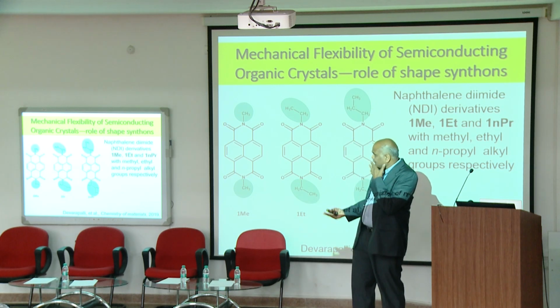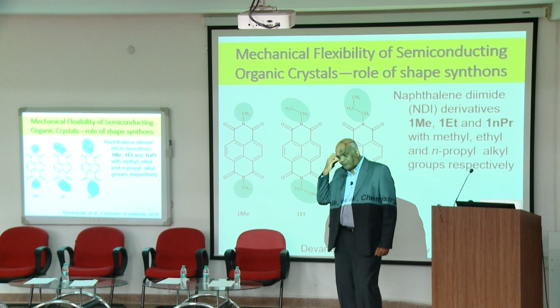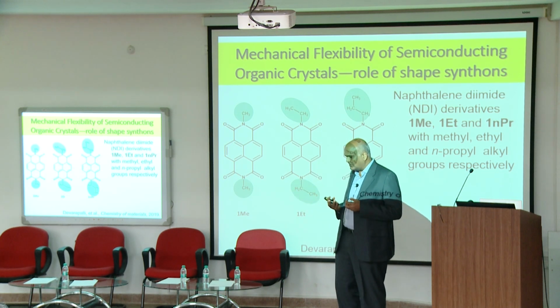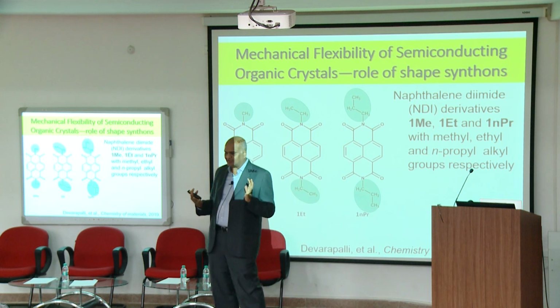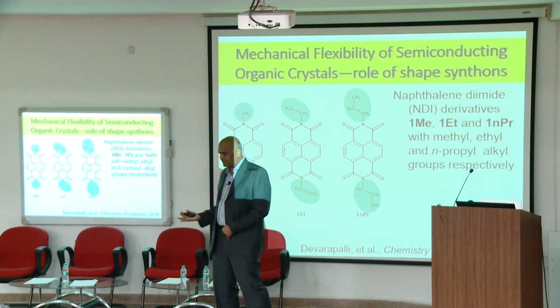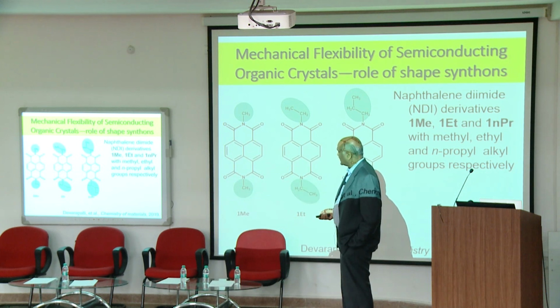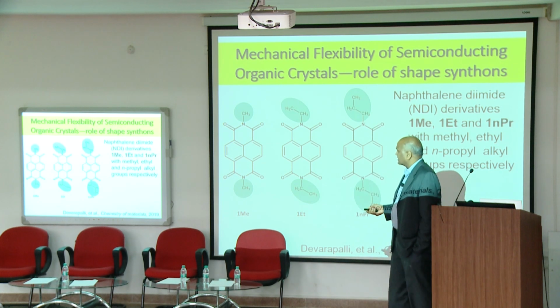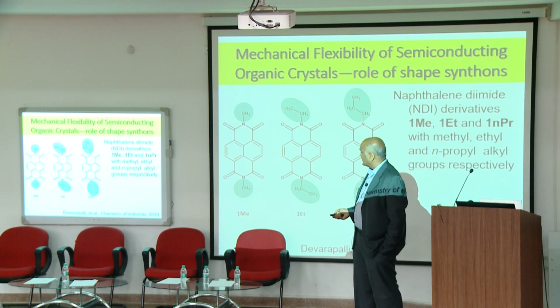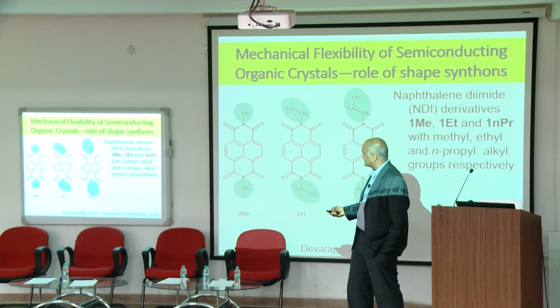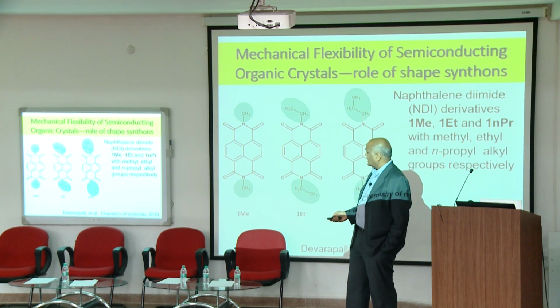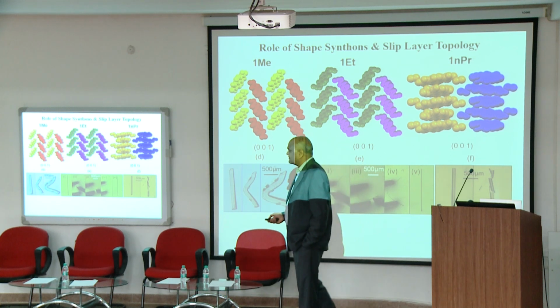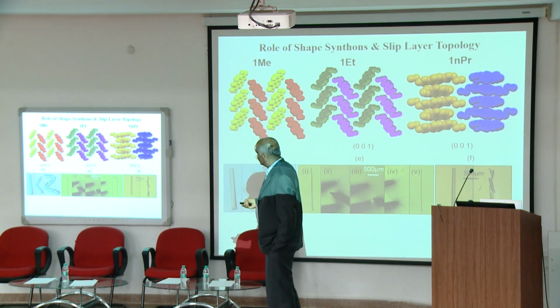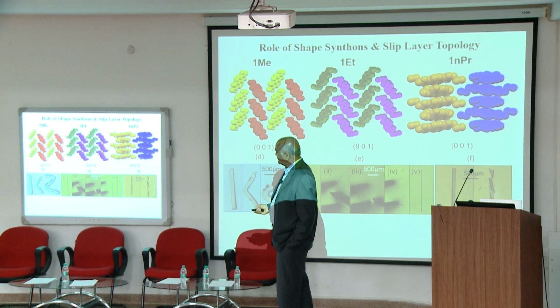More recently we have been looking at synthons. Again, this concept of synthons as the building blocks of crystal structures, the crystal engineering concept, started here. So this is the work done with Malla Reddy. We took these diimide derivatives with methyl, ethyl, and N-propyl alkyl groups, and you see the base molecule is the same, but these alkyl chain lengths are different, longer, and as a result the crystal structures are different, and because the crystal packing is different, this material is very soft.